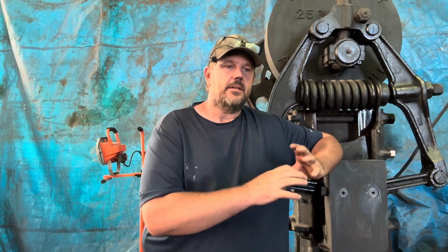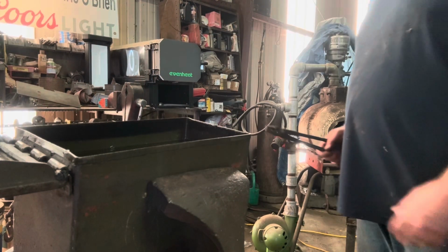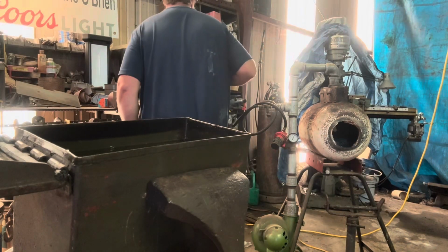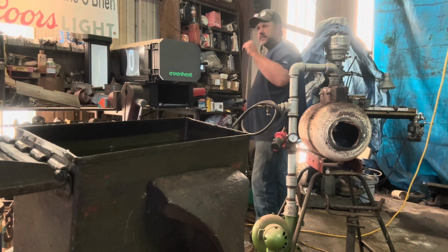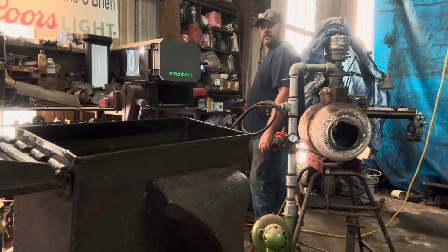The reason you don't want a large grain is because after you heat treat, it will have those large grains, and those grains make the blade brittle and more easily broken. You can chip edges, or break a knife completely in half. So you want to do those grain reduction cycles to bring the grain back down to the size it was before all the forging. That will make a much stronger blade than if you didn't do that. And of course, on the heat treatment of my knife, my microphone died, so there is no audio with this section of the video.